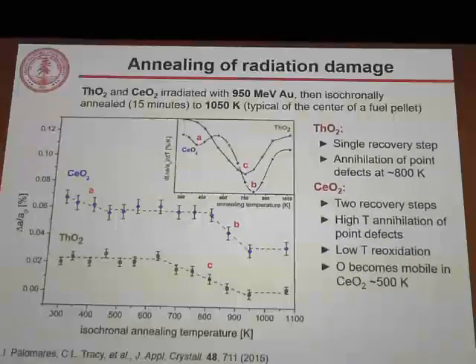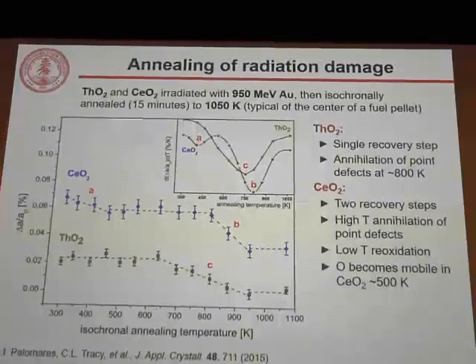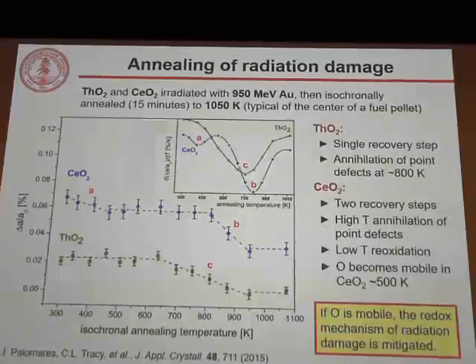And we know that oxygen becomes mobile in cerium dioxide at about 500 Kelvin because it's often studied for use as a solid ionic conductor. And if we look at the derivative of the unit cell change as a function of temperature, we see that's really a good match. It's just a little bit before this mobility comes around and oxygen starts recovering that we start seeing this structural recovery. So what this teaches us is that there's a mechanism, once we understand the mode of damage, by which it can be mitigated. If we make oxygen mobile, this redox effect won't be so influential, won't reduce the radiation tolerance